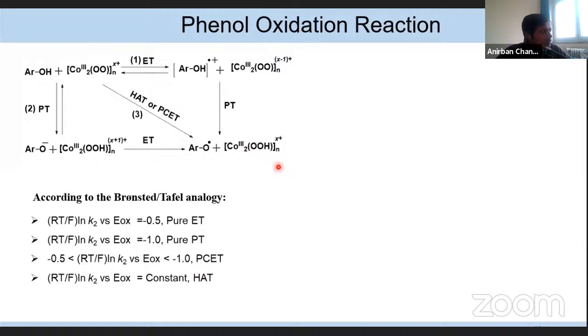So if we plot RT/F ln K2 versus E, if it comes around minus 0.5, then it's a pure electron transfer. If this value comes at minus 1.0, it is a pure proton transfer process, but for a PCET process this value should lie in between minus 0.5 and minus 1.0, but for a hydrogen atom transfer process this value should be constant.